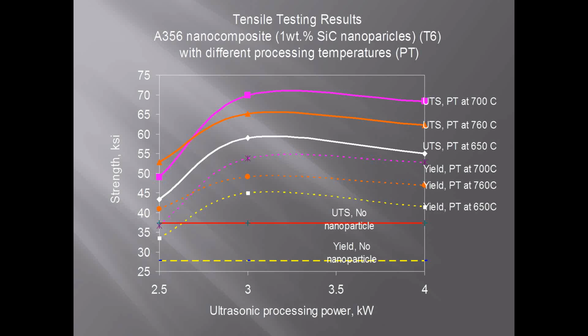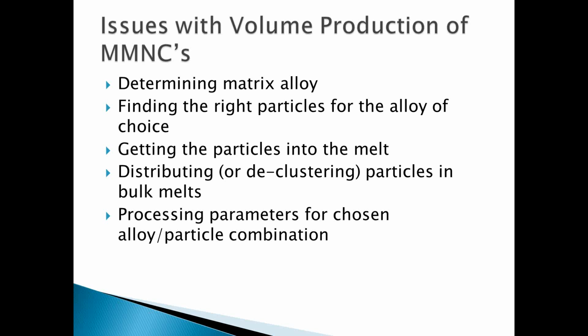nano-reinforced casting. And this is some of the work that came out of that original American Foundry Society sponsored program, where in small batches, and we're talking batch sizes of a pound or two, they were able to demonstrate a doubling of mechanical properties in the A356 using a 1 weight percent silicon carbide nanoparticle. And these results were the basis for a larger program sponsored by the National Institute of Standards in order to attempt to scale up this technology into batches that, as foundry people, we would actually be interested in doing and customers would be interested in buying.